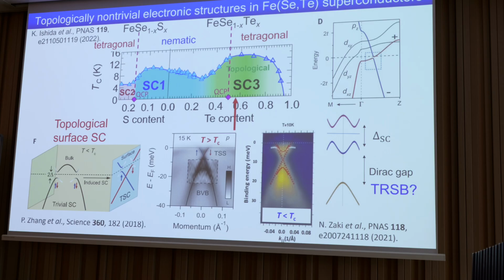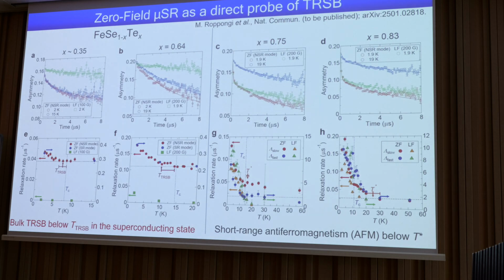So I extended our zero field muSR measurements to the tellurium side, and we see also that the relaxation rate is going up below TC. So we believe that we also have time reversal symmetry breaking in iron selenium tellurium.